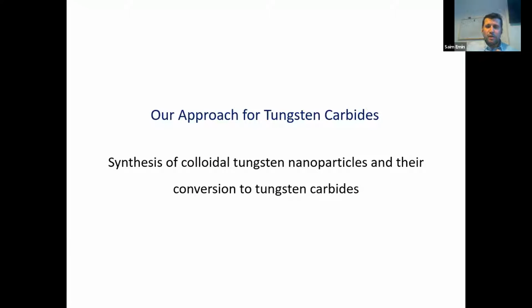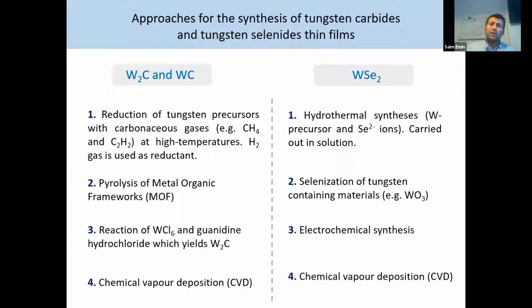And as I said, these metal carbides, transition metal carbides, are very good candidates, especially tungsten carbides, because they are very robust. They are stable. They can operate in acidic and in alkaline environments. Metal carbides are good for hydrogen evolution studies. Metal selenides also are good for hydrogen evolution studies. Some are even bifunctional, like metal phosphides. They can also be used for water oxidation studies.